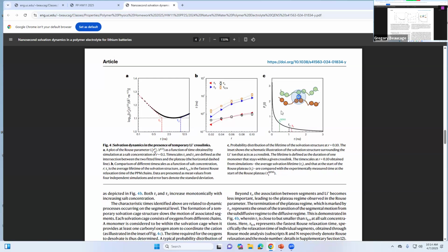You could also get this from the NMR measurement in that other paper, where they do a cross correlation, and you see the cross correlation peak. The area of that peak would give you the probability of that association existing. You could take the area of the carboxyls and the area of the cross correlation in the 2D plot, and take the ratio of those two, which would give you the probability that it existed, out of all the carboxyls.